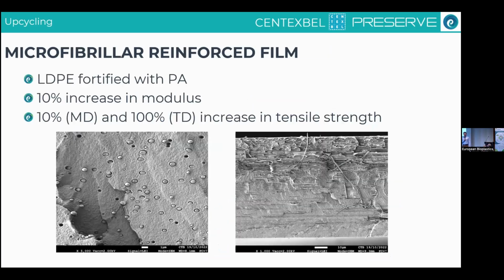First of all, when we look at self-reinforced materials, the goal here is to look at what happens if we blend different materials that are supposed to be immiscible. An example here is using a high fraction of low density polyethylene and blending this with a very small fraction of polyamide. If we do this properly in a film extrusion, we will see that the polyamide will form microfibril structures within the film itself.